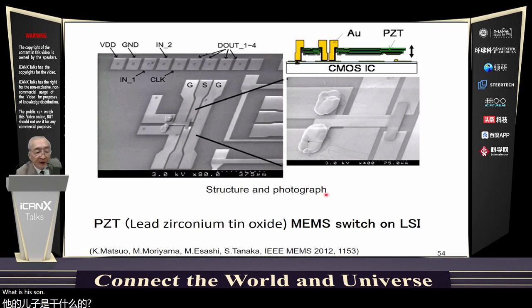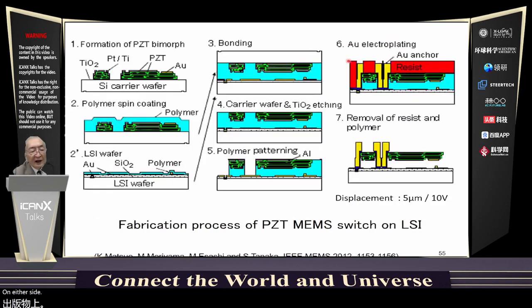Lead zirconate titanate, PZT, has good piezoelectric property. RF MEMS switch using PZT bimorph was fabricated on LSI. The fabrication process is shown in this slide. The PZT film was deposited by sol-gel method and annealed at 680 degrees centigrade on a silicon carrier wafer in one.